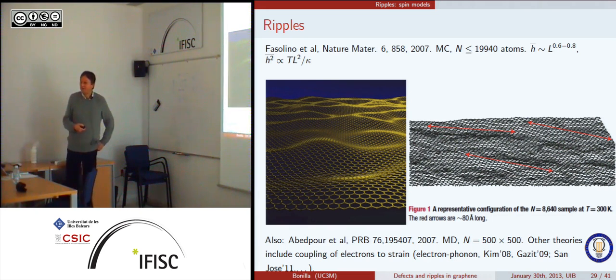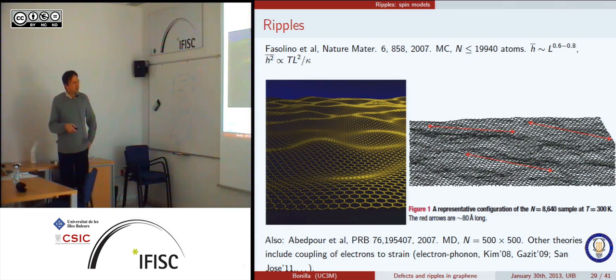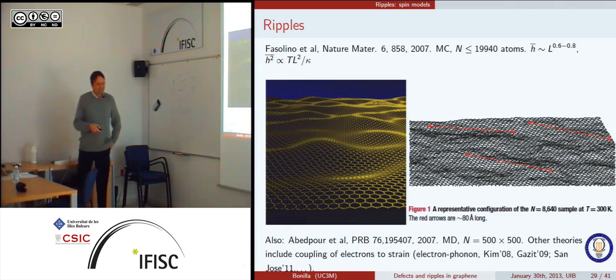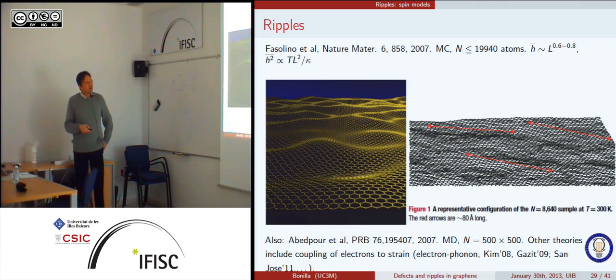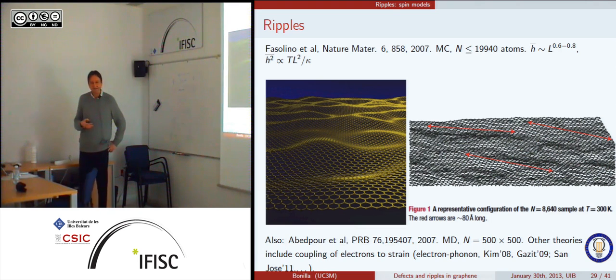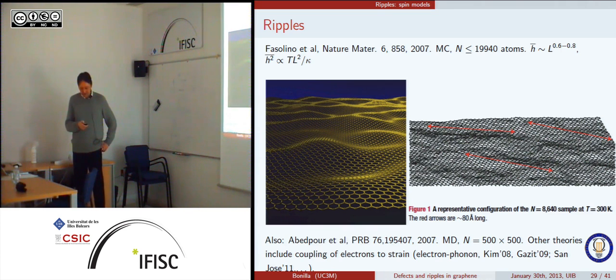And now, what is the origin of these ripples that you see? There are a bunch of theories. For instance, most of the quantum theories include electron-phonon coupling in different ways. And for instance, this paper by Pablo San Jose and Guinea and so on, they argue that the ripples come because at 0 Kelvin, with the special variety of coupling that they use, you can show that there is a quantum phase transition according to which the bending modulus goes to 0. So if the bending modulus goes to 0, then the sheet cannot be kept in a planar configuration, and you get the ripples. All these explanations are kind of equilibrium